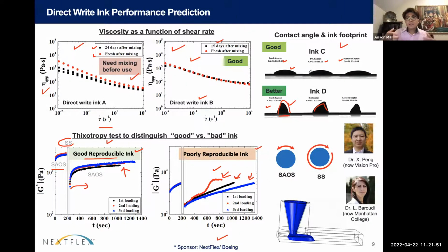So doing this kind of contact angle measurement, again, is a pre-screening. If you have a lot of options in terms of inks that you want to work with, or inks that you formulate in your own lab, you want to at least get a sense before you set up the whole printer and waste all kinds of materials. I always suggest you run some rheology tests and also some contact angle measurements that at least give you a pretty good sense of how well this ink is going to behave when you do this kind of direct ink writing. And back then also my former postdoc, Lena, she did some simulations.